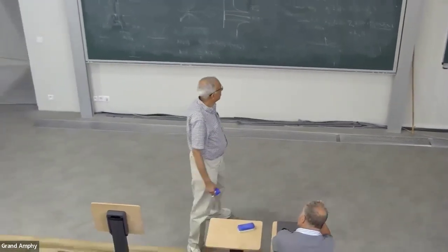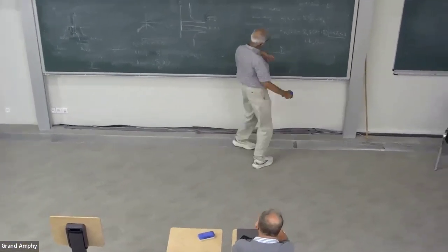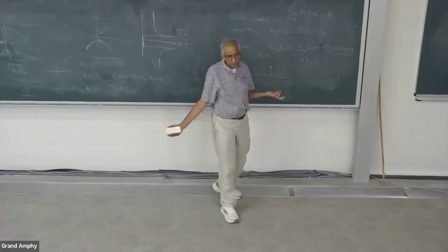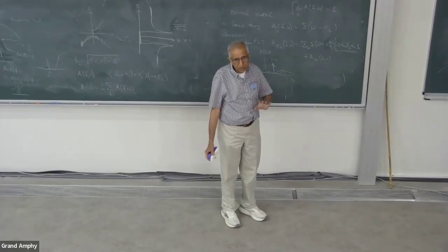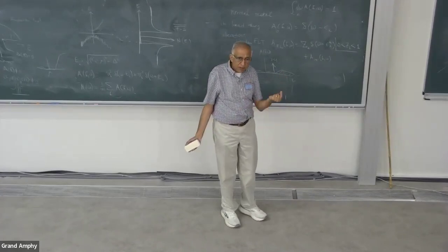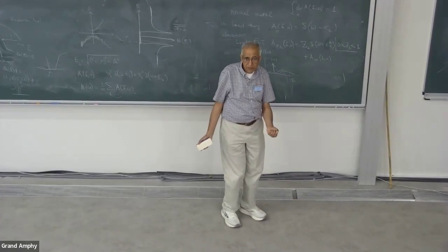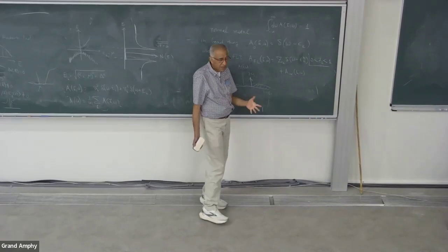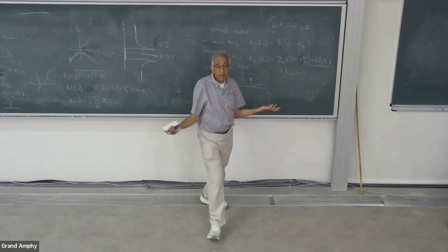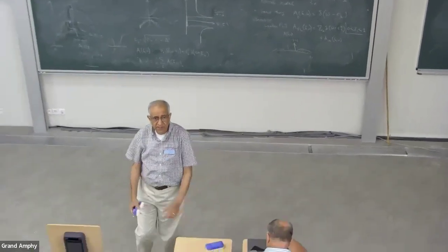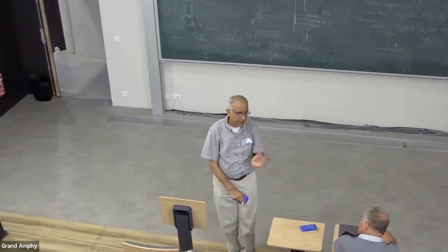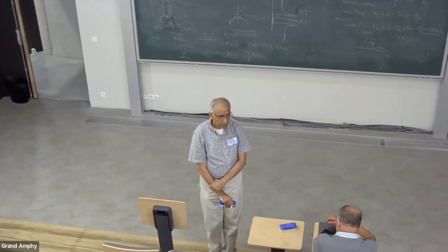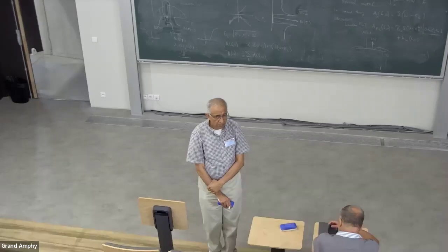experiments. So at least in cuprates, it's known that when you're above Tc, to the best of anyone's ability to measure things, there is no pole, there is no Z. It's broad as hell. But when you go below the superconducting transition, and mostly studied in BSCCO, because that's where ARPES exists, you suddenly see a sharp peak and other stuff. And you can do that in a k-resolved way. So it means that the superconducting condensate can be in some cases described by